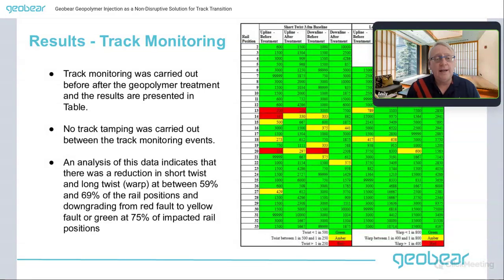So analysis of this data indicates that there was a reduction in short twist and long twist warp at between 59% and 69% of the rail positions, and a downgrading from red fault to yellow or green at 75% of the impacted rail positions. So overall, there was an improvement in the track monitoring, and we're advised by Irish Rail that they're quite happy with this performance, and that the line speed could be restored based on this.